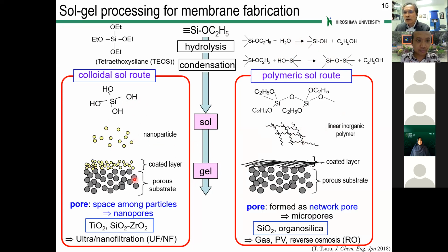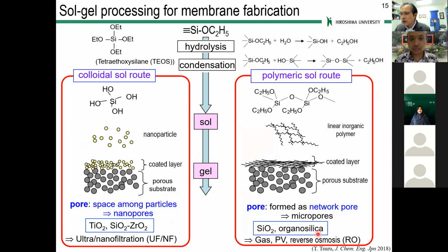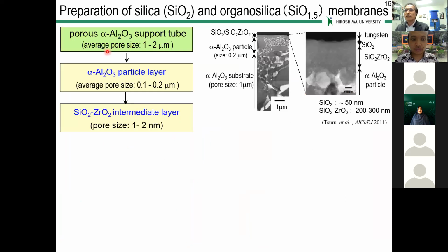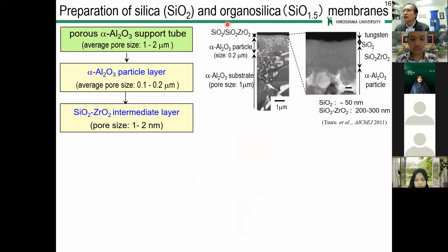These sols can be coated on the support. In the case of the colloidal sol, the particles are just several nanometers, so the pores are formed as space among the particles, which is suitable to fabricate nanopores, such as titania or silica-zirconia, for ultra or nanofiltration membranes. In the case of the polymeric sol, we coat it on the support. Pores are formed as network pores, which give micropores. In the case of silica or organosilica, this system is suitable for gas separation, pervaporation, or reverse osmosis.